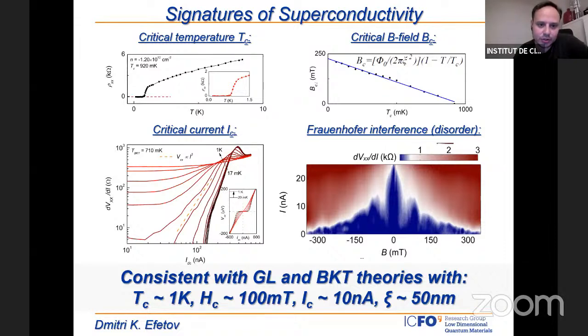So it is not completely unusual to see linear temperature dependence in graphene, because it's defined by the Bloch-Grüneisen temperature. Also, in this whole debate, what's really important is the slope of this temperature dependence. If you do estimates from just a very simple electron-phonon interaction, as done by Das Sarma, for example, in the theory used in previous work, you actually get relatively close to this linear temperature dependence. You get within a factor of 3 or 4, so you're not factors of 10 off in describing the slope.